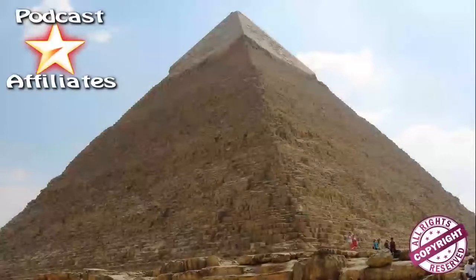95%, to which that contained clay or to which clay was added, and then the natron, the salt, sodium carbonate, and then lime. That results from the calcination of limestone. This is lime, slaked lime. For the people who understand chemistry, this is calcium hydroxide, Ca(OH)2, and so it has to be manufactured.